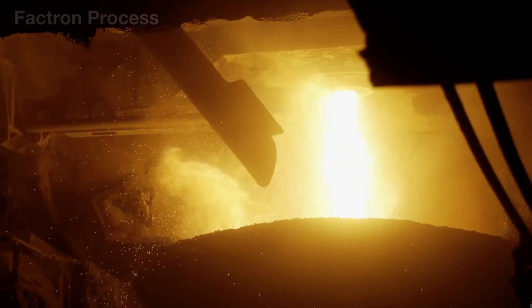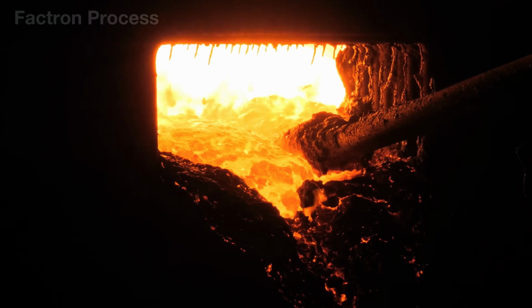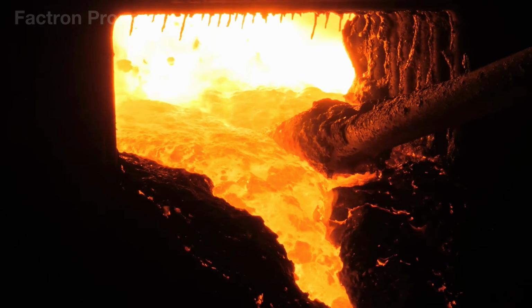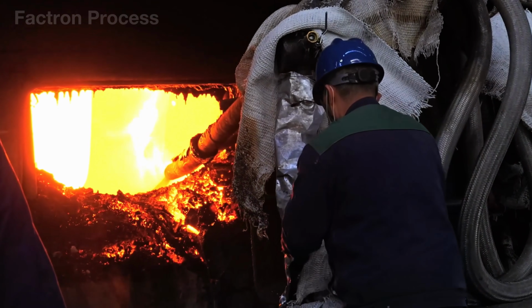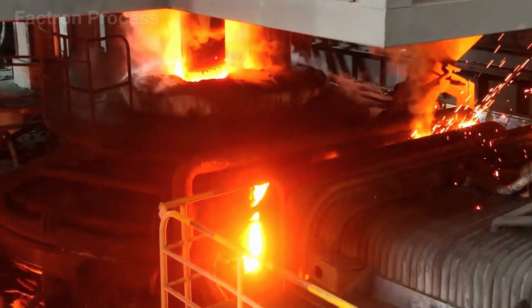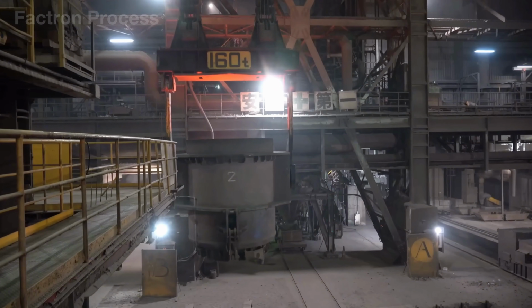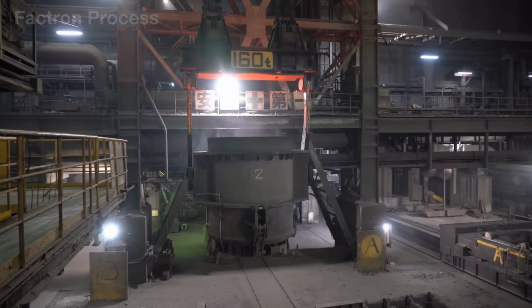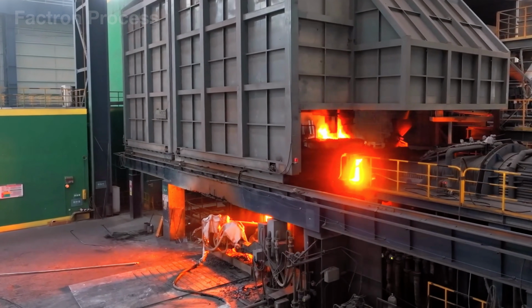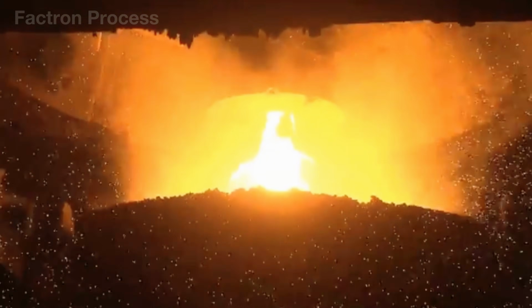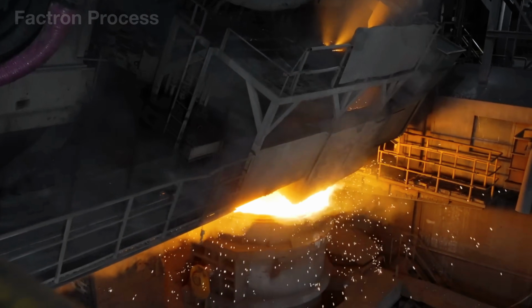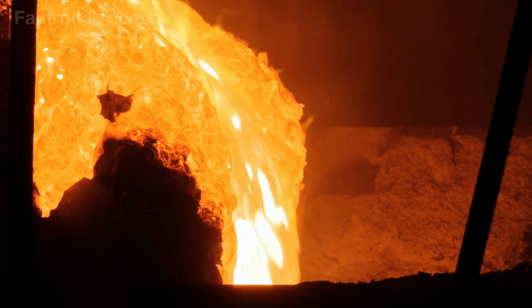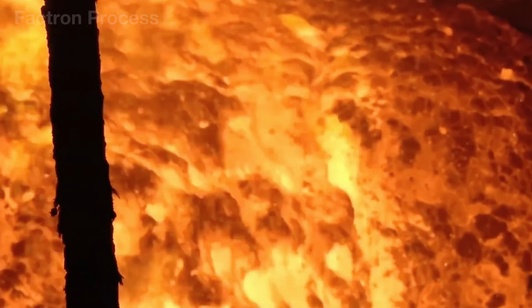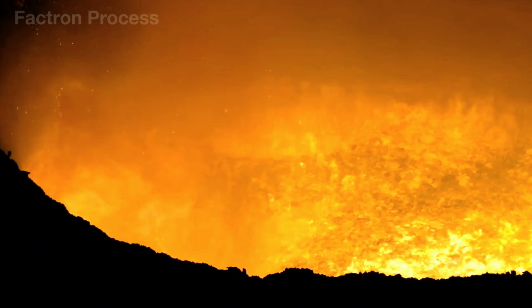During the melting process, quicklime and dolomite are added to combine with oxidized impurities, forming a thick layer of foamy slag that floats on the surface of the molten steel. This slag acts as a protective shield, preventing the liquid steel from absorbing gases from the air while helping the furnace retain heat. Sensors and spectroscopic analysis systems continuously monitor the process to ensure that the alloy composition meets the required specifications. Finally, the glowing stream of molten steel is tilted into a ladle furnace, where precise amounts of alloys such as manganese and chromium are added, preparing it to be reborn as high-quality, new steel billets.